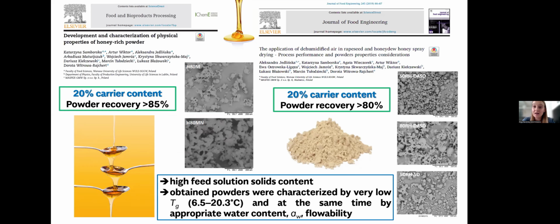And in both these studies, by air dehumidification, we could lower the drying air temperature. So it was possible to lower the carrier content even down to 20%. And at the same time, which was very interesting, we observed a very high powder recovery, over 80% or over 85%. At the same time, as you can see at the bottom in this blue frame, these powders that were produced were obviously free-flowing, so we did not observe any problems with their functionality. However, they were characterized by quite low glass transition temperature, from around 7 to 20 Celsius degrees, but after spray drying, after producing them, at the same time, they presented appropriate water content, appropriate water activity, and satisfactory flowability. And water content and water activity, when they are satisfactory and appropriate, ensure the powder's stability.